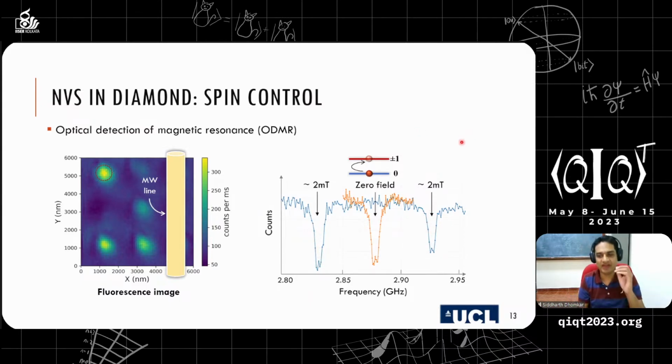So this becomes a very nice magnetic field sensor, very sensitive to local magnetic fields. You have a single NV center, you bring it close to a certain magnetic field, it will interact with that static magnetic field due to Zeeman interaction, and if you apply microwave frequencies, you will be able to decode what kind of field it's experiencing. That's why it becomes a very nice quantum sensor.